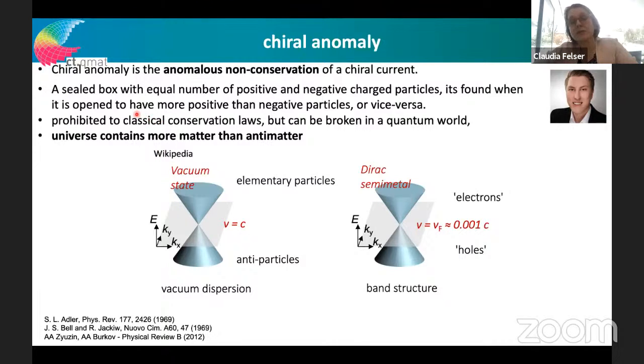The first measurement we do in transport is to look for the so-called chiral anomaly, which is a special solution of the Dirac equation, which was invented by Weyl, and later also by other people who have done this very careful mathematical investigation. Depending on how your experiment is set up, you can find an anomalous non-conservation of a chiral current.